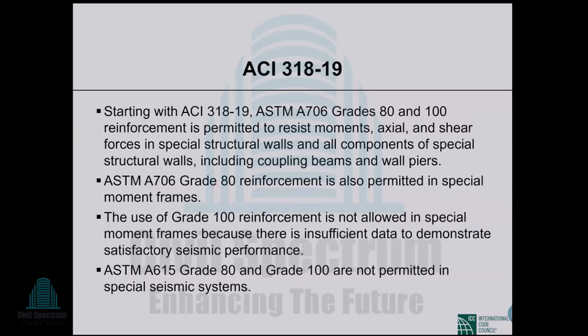In special moment frames, grade 100 is not permitted, but grade 80 of ASTM A706 is permitted. The use of grade 100 reinforcement is not allowed in special moment frames because there is insufficient data to demonstrate its performance. ASTM A615 grade 80 and grade 100 are not permitted in special seismic systems. In our case too, we don't permit grade 80 and grade 100 produced according to ASTM A615. But grade 80 is permitted according to ACI 318-19, and for special structural walls, even grade 100 is permitted.